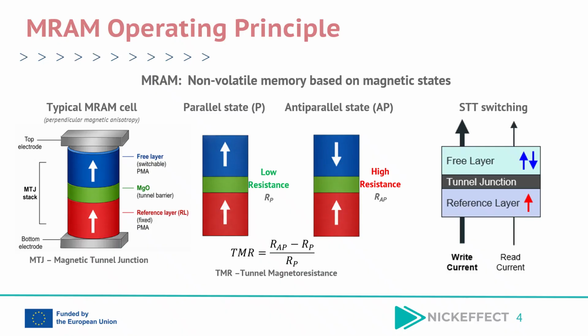In modern perpendicular MRAM structures, the magnetization is oriented out of plane due to the perpendicular magnetic anisotropy. Information is encoded through the relative orientation of magnetization in the two layers. The parallel state corresponds to low resistance, while the antiparallel state exhibits high resistance. Depending on the device design, these states can represent logical 0 or 1. The resistance difference is described by the tunnel magnetoresistance ratio, or TMR, shown at the bottom of the slide. A high TMR value is essential for reliable device readout.